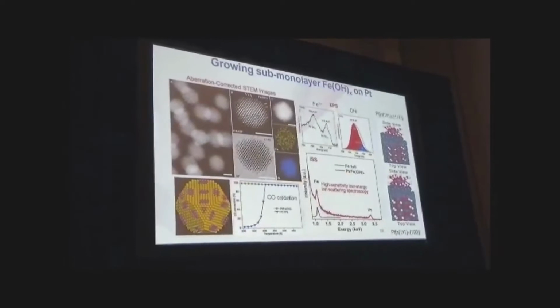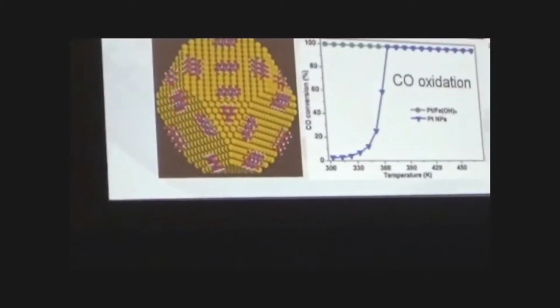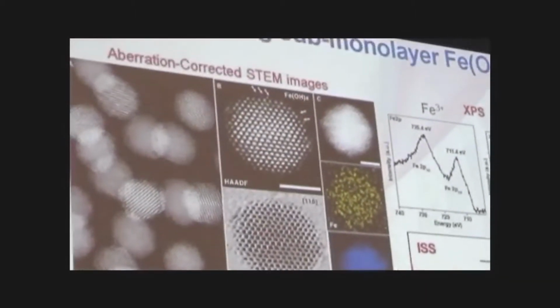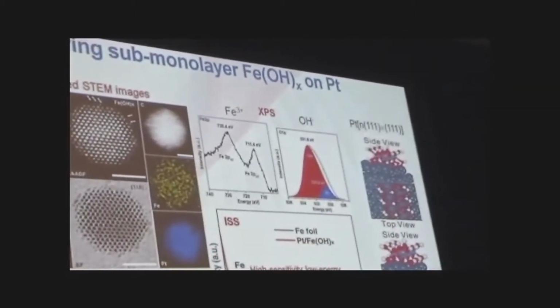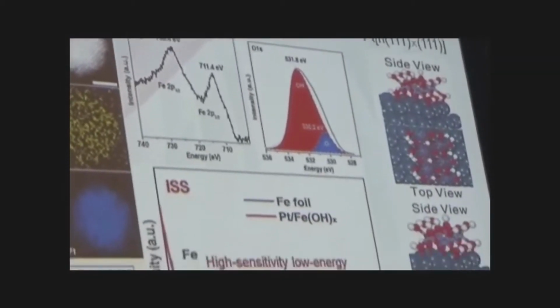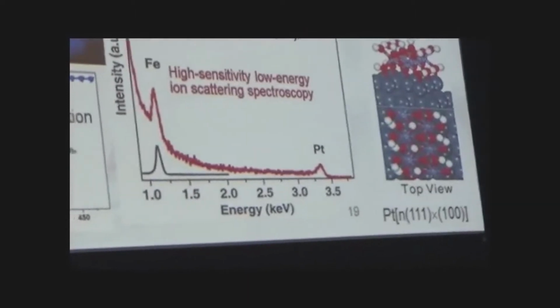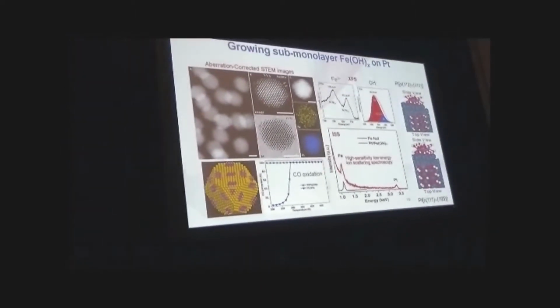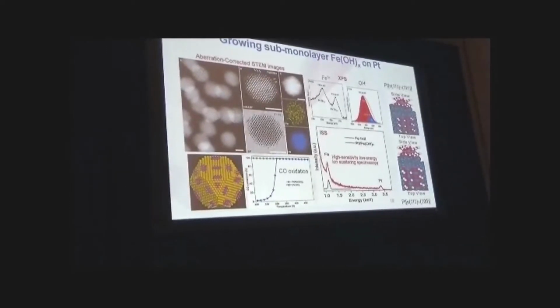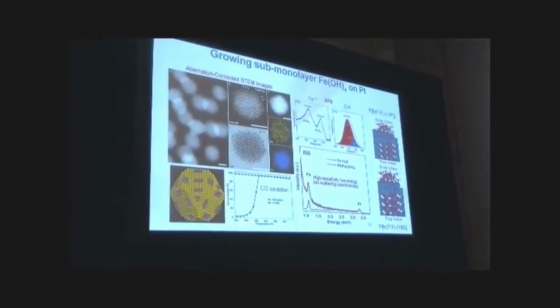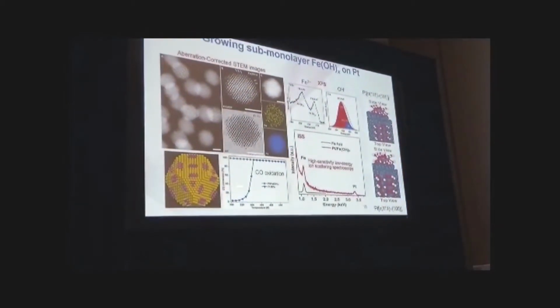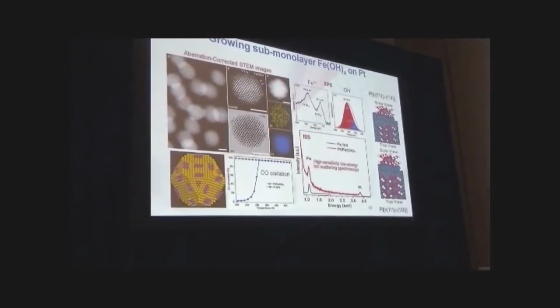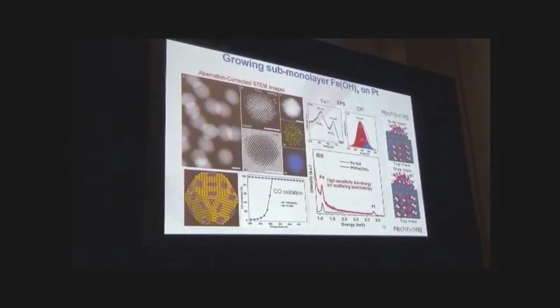Here is the example. We can use iron hydroxide on platinum. Here we use CO oxidation as the model reaction. You can see that when we use Pt nanoparticles, the reaction temperature for 100% conversion is very high, about 100 degrees C. When we use submonolayer iron hydroxide on platinum, you can see that the temperature decreases. We can get 100% conversion at room temperature. So it's low temperature CO oxidation.